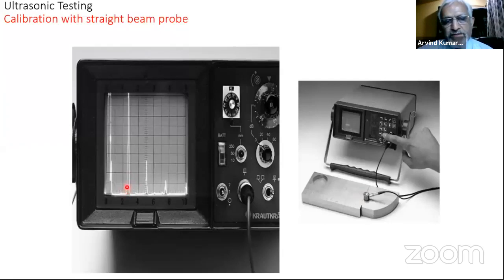I'm seeing 4 peaks. 1, 2, 3, and the fourth one. Fourth peak means I have 25 mm, 50 mm, 75 mm, and 100 mm. So if I have 4 peaks within my full range, I am having 25 into 4, that is a 100 mm range. My range is 100 mm. If I want a range of 50 mm using the same thick block, then what I need to do is take the second echo, this is 25 and this is 50. This 50, I will turn the knobs, the delay knob, and bring it to the full range. So my entire range will become 0 to 50. This is how the calibration is done using a single crystal normal probe.